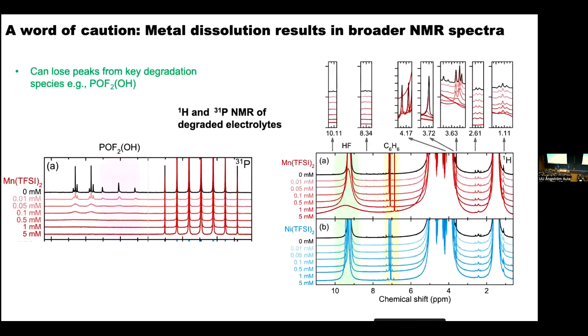And what she showed very beautifully was that this broadening was worse for some of the components you were looking for. So this is an example where she's putting manganese into a solution containing POF2OH, and this is one of the degradation products of PF6 and water. But if you have a lot of manganese around, you can't see it. And the same is true of a whole series of other proton degradation products.